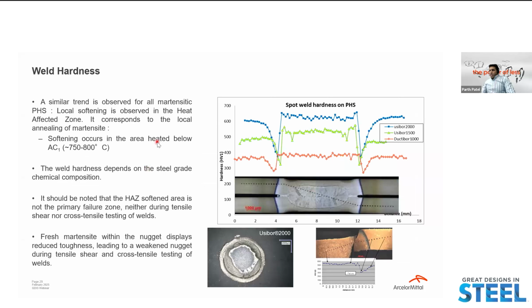Just quickly touch upon hardness, because most of our martensitic products, Ductibor 1000, Usibor 1500 or Usibor 2000, are all fully martensitic product. The only difference is the different carbon percentage. So the phenomena of hardness is very similar. You will have a drop in hardness in the soft zone area. Softening is occurring because the heated areas are below AC1 temperature in this zone.